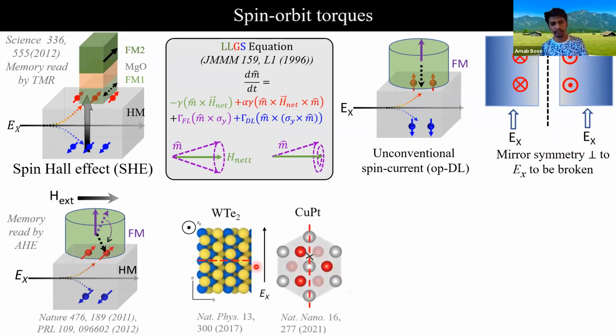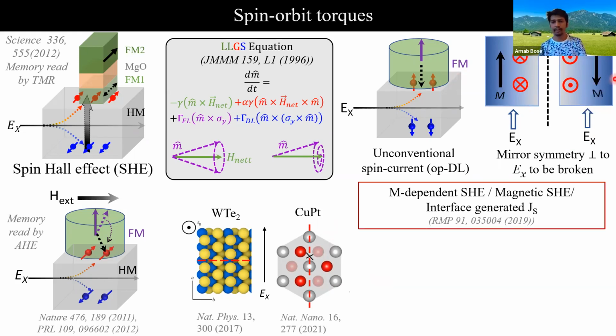This has been reported for the first time in tungsten ditelluride, and also recently in different materials such as single crystal copper platinum. But this is not the only way that we can break the symmetry. For example, we can have magnetic ordering in the system that also breaks the symmetry. So depending on the direction of magnetization, we can also have this sort of exotic spin current, which is also referred to as the magnetic spin Hall effect.